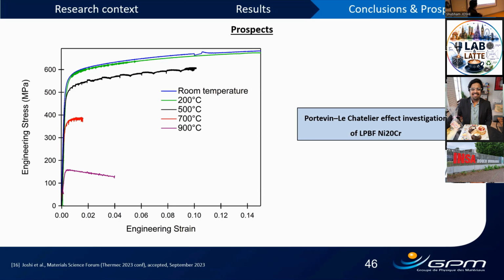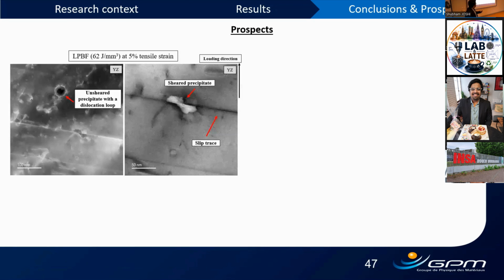So clearly, somehow, the Portevin-Le Chatelier effect should be the cause for investigation. And finally, I completely discarded the influence of oxides, which probably form because of the trace elements manganese, aluminium, silicon, and so on. But if we look at these curves, we can clearly see that dislocations are looping around these oxides, and these oxides, mind you, should be incoherent with the matrix, and still it is interacting.